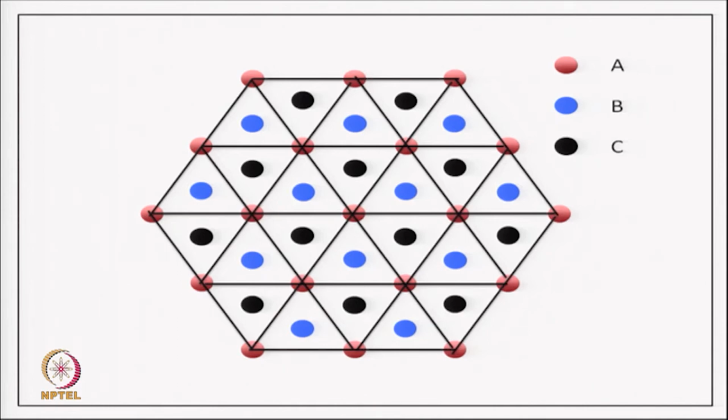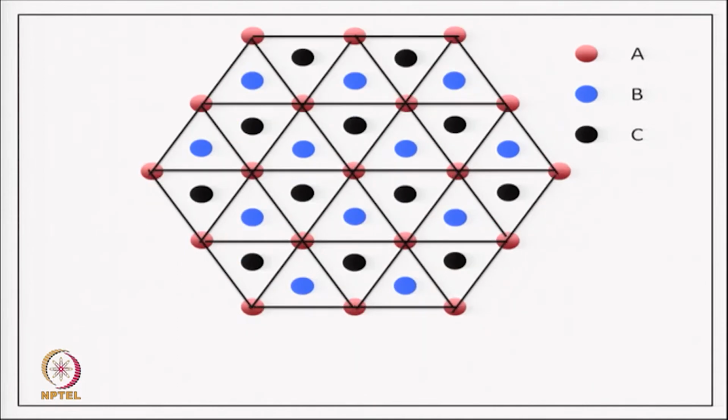To find the lattice of this structure, one important question is whether all atoms are identical in the lattice sense or not. Recall that in the hexagonal close packed structure with AB stacking we had done this exercise, and there, to our surprise in a way, we found that the A and B layer atoms are not equivalent in the lattice sense. So, the HCP crystal structure had 2 different kinds of atoms, or two atoms in the motif. We do the same exercise here.